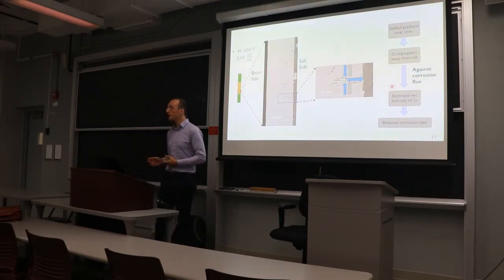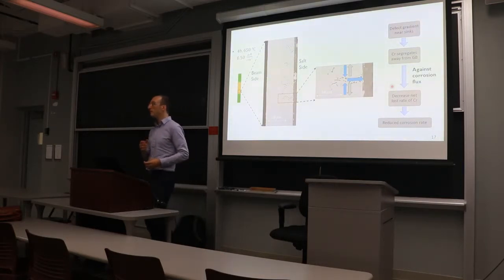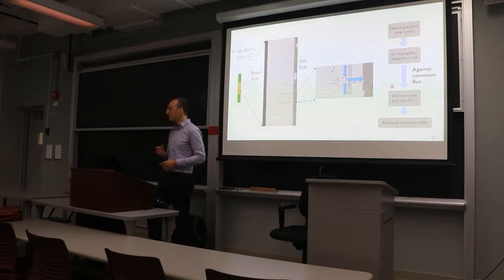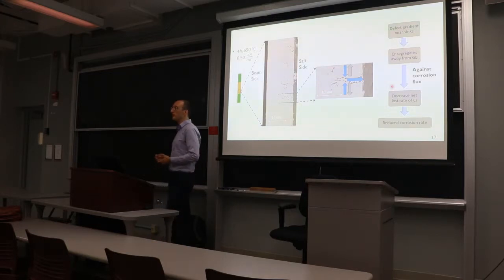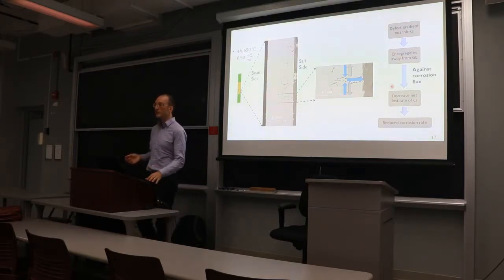There are regions where this shouldn't work. If the temperature gets too high, you switch to a bulk or an intragranular corrosion mechanism, and this shouldn't work anymore. You also won't be able to support that much of a chromium depletion. So once you pass 700 C or so, which we've done in the lab, this effect shuts off, and you get an acceleration of corrosion with irradiation. But this should also work in liquid metals, because in liquid metals, in the reducing condition, the corrosion mechanism is often chromium depletion.